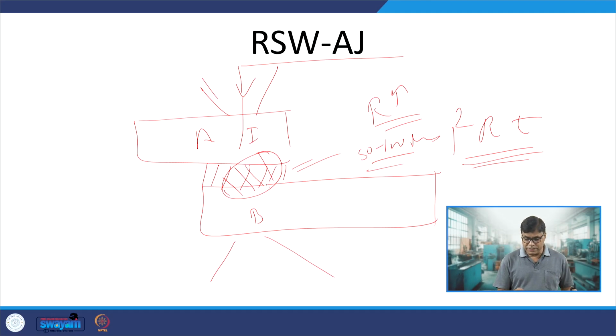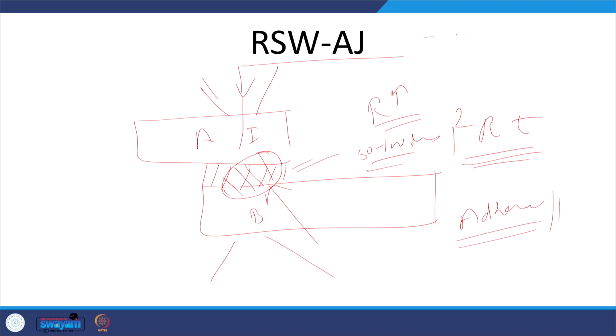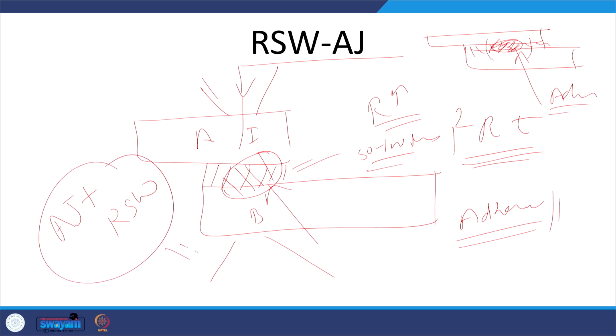So, in this process of excessive heat generation by the resistance welding, the adhesive is certainly thermally damaged. Say if this is the area where our adhesive bond was initially developed everywhere, if the spot weld has been developed in this location, then certainly in this area our adhesive will be thermally damaged. So, it will evaporate completely. And in the neighboring areas also, thermal decomposition of the adhesive can take place. But other areas where the heating has not been there, their adhesive will remain intact and it will contribute towards the joint strength. So, in this kind of hybrid joining, adhesive joint clubbed with resistance spot welding, both contribute towards the joint strength.